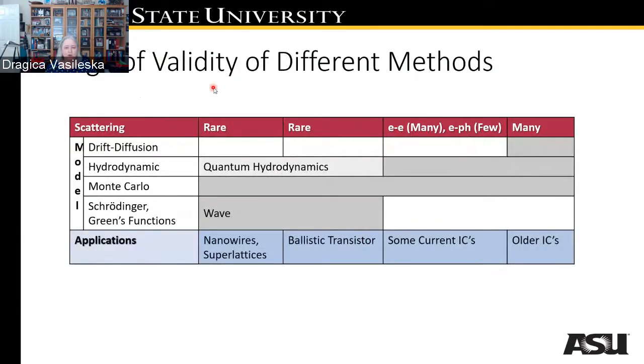The range of validity of different methods is also illustrated in this slide, where again I'm reiterating the drift diffusion model is valid when we have many scattering events. Quantum hydrodynamic model can be used when we have rare scattering events, and Monte Carlo device simulations can also be utilized, for example, in modeling of nanowires, superlattices, and ballistic transistors. But if we go beyond these length scales, in other words, if we go to smaller length scales where the wave nature starts to dominate the device behavior, we either need to resort to direct solution of the many-body Schrödinger equation or the Green's function approaches.